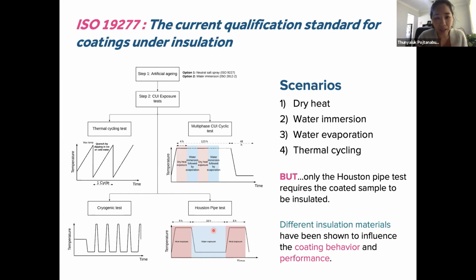The Houston pipe test is only in the standard as an optional test. It's not required. But there's a study done and presented at NACE a few years ago that shows that different insulation materials will affect the coating behavior and performance. One of the coatings studied in that conference paper performed much better when it was insulated with calcium silicate compared to when it was insulated with mineral wool insulation. So that is something to take into account when looking at the qualification of the coating.